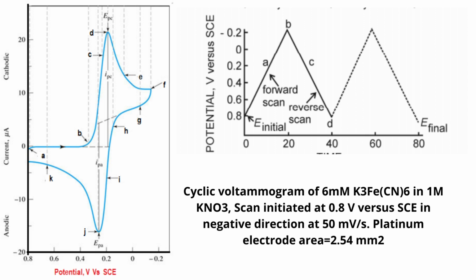Now the cyclic voltammogram is obtained. It is clear that any potential positive of 0.40 volt would be suitable as the initial potential, as the reduction of ferricyanide would not occur when the potential is applied. This procedure avoids inadvertent electrolysis as a result of applying the initial potential. In the forward scan, ferrocyanide is electrochemically generated from ferricyanide as indicated by the cathodic current, while in the reverse scan ferrocyanide is oxidized back to ferricyanide as indicated by the anodic current.